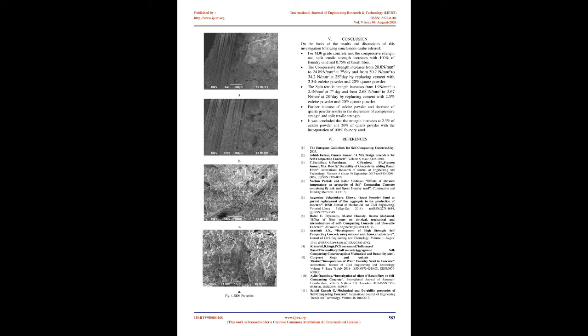In the above results, the L-box ratio H2/H1 for the mixes was above 0.8, which is as per EFNARC standards. The U-box difference in height of concrete in the 2 compartments was within the properties of self-compacting concrete. In terms of slump flow, all SCCs exhibited satisfactory slump flows within the prescribed range, which is an indication of good deformability. All the fresh property values were in good agreement for flowability and passing ability with the values given by European guidelines.